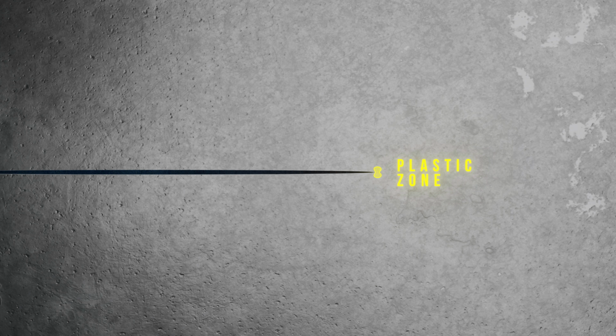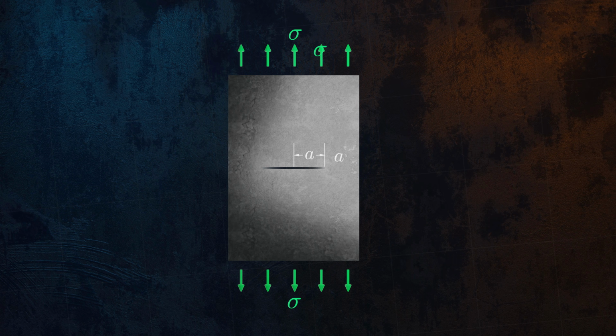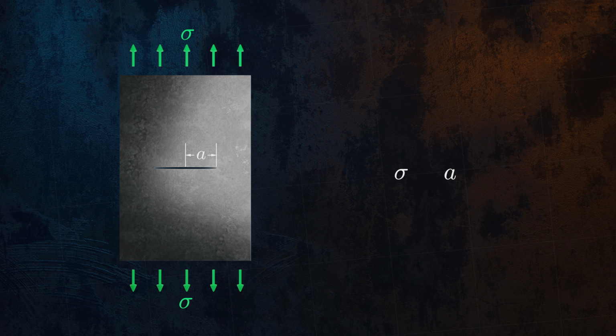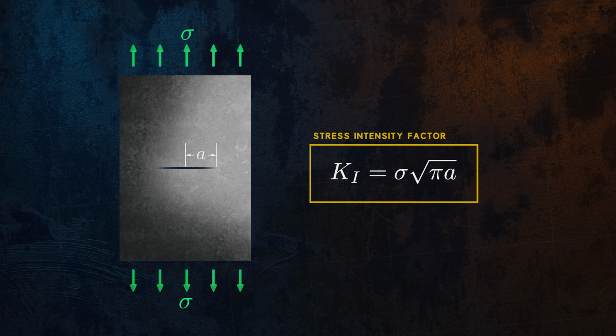This makes the stress state at the tip of a crack extremely complex. But luckily for engineers, if plastic deformation only occurs in a very small zone at the crack tip, the severity of the crack depends on just 2 things, the applied stress and the crack size. These can be combined into a parameter called the stress intensity factor, a single value that describes how severe the stress state is at the crack tip.